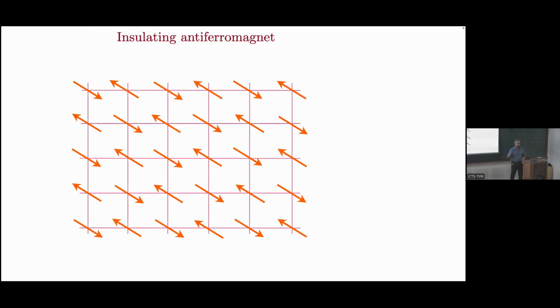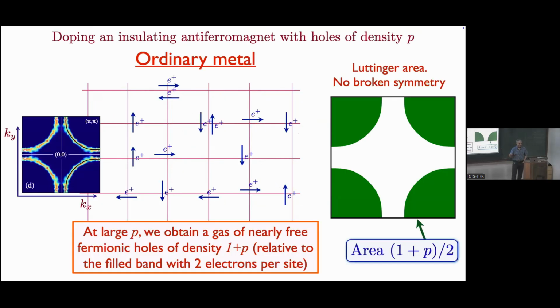If you have an insulating antiferromagnet, of course, it's an insulator, there's no Fermi surface. If you have large P, then you have essentially free holes. I'll talk in terms of holes rather than electrons. Then the area of the Fermi surface is 1 plus P, which is the total number of holes relative to the filled band, divided by 2, a factor of 2 for spin.